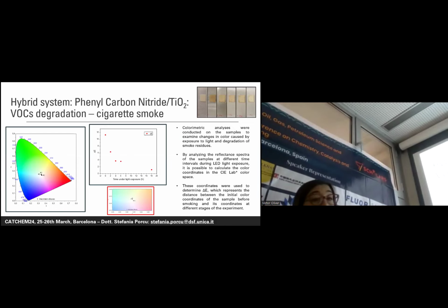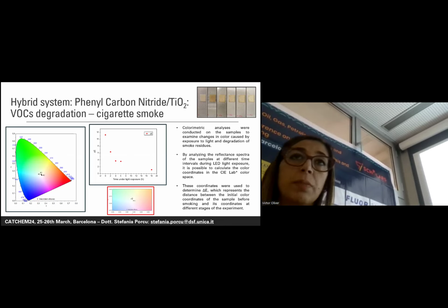We studied it even through colorimetric analysis, in which we studied the change in color during the exposure to the light. By analyzing the reflectance spectra of the samples at different times of exposure to LED light, we calculated the CIELAB color coordinates in the color space. So we were able to obtain the total variation of color, called delta E, during all the intervals of time. What we found was that the color of our film when we started the experiment and when the experiment finished was exactly the same, while the color during the photodegradation process changed with respect to the amount of pollutants present on the surface.